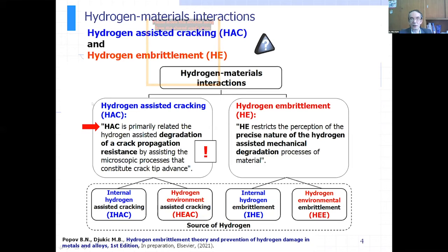Hydrogen materials interaction is a complex term, but if we talk about preventive maintenance and maintenance engineering, they are mostly interested in hydrogen-assisted cracking. What is hydrogen-assisted cracking? It is hydrogen-assisted degradation of crack propagation resistance by assisting the microscopic processes that constitute crack tip advance. Due to the degradation of crack propagation resistance, the components finally fail. On the other hand, hydrogen embrittlement is restricted to the perception of the precise nature of the hydrogen-assisted mechanical degradation, and we have various models on which the degradation of crack propagation due to hydrogen embrittlement exists.